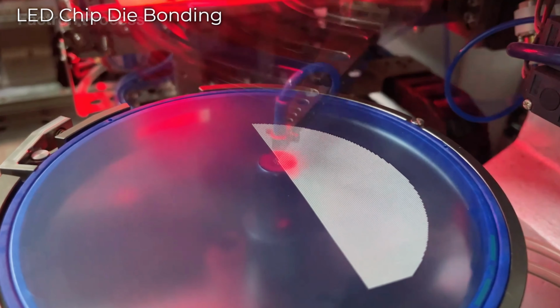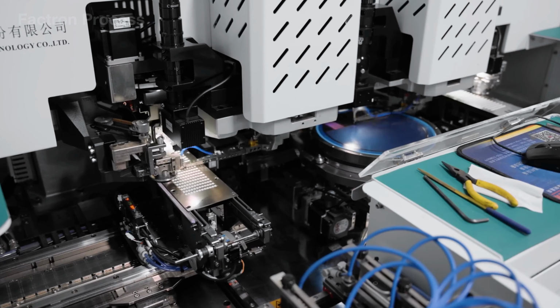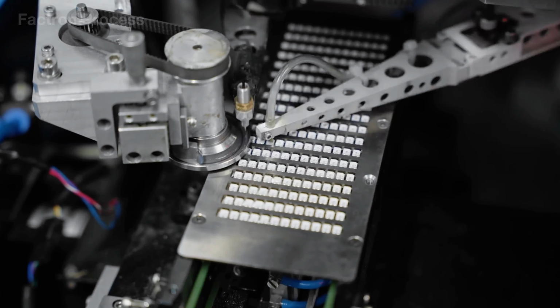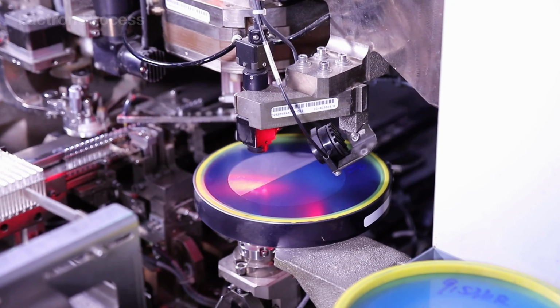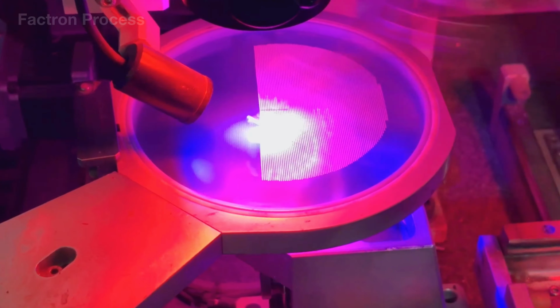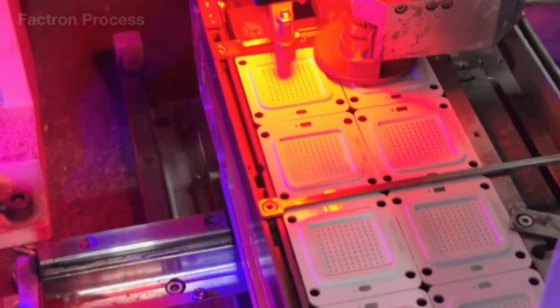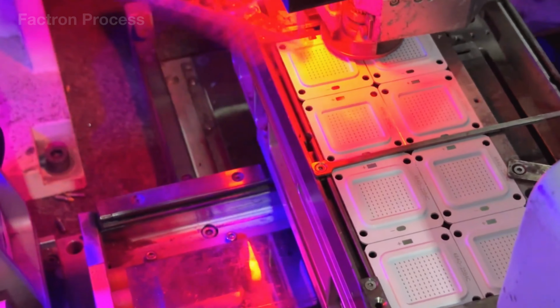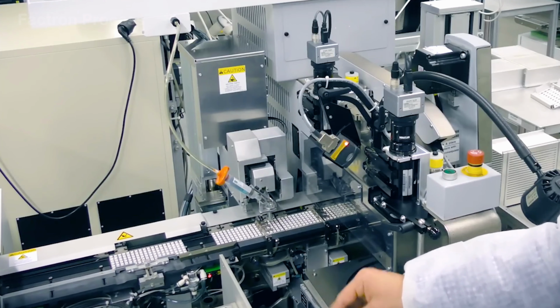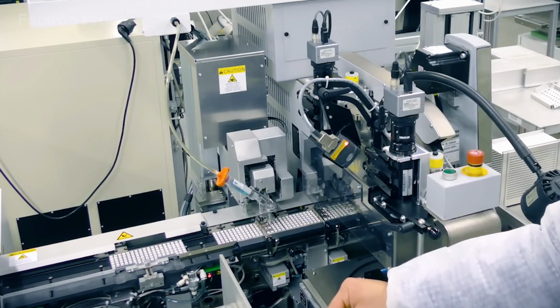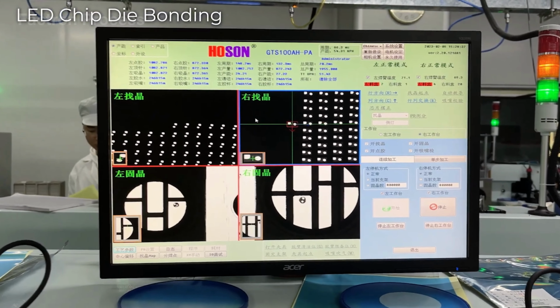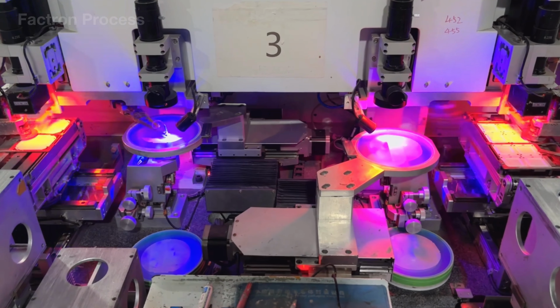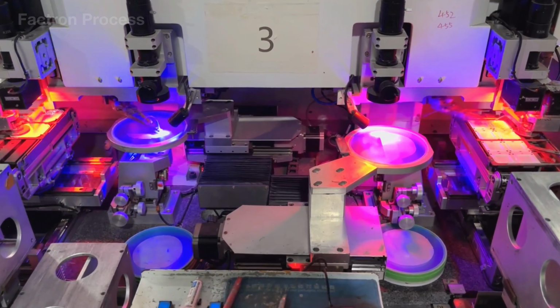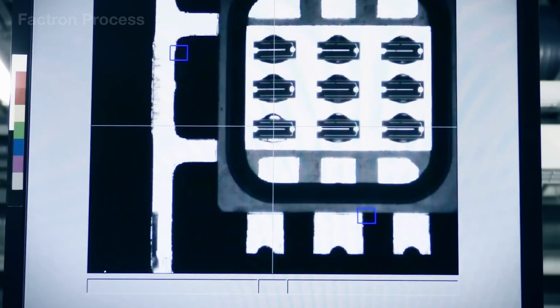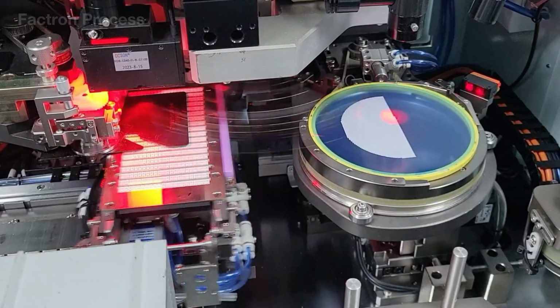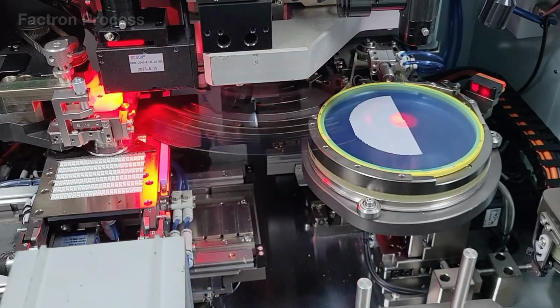Remarkably, the system's speed is barely affected by the microscopic size of the chips. Modern die bonding machines can mount between 15,000 and more than 30,000 chips per hour, equivalent to roughly 4 to 8 chips every second, while maintaining near-perfect accuracy. A misalignment of only a few dozen micrometers can cause the wire bonding process in the next stage to fail or reduce the LED's ability to dissipate heat, forcing the entire component to be rejected.